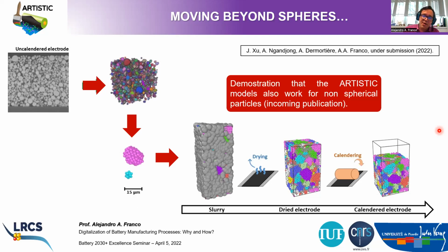And here, what we did is we start from tomography images, micro CT tomography images. Then we have developed an algorithm which is able to extract the real particle morphologies from these micro CT images. And then we perform all the simulations of the slurry, the drying, and the calendering using the real particle morphologies, okay? And then, of course, we compare the outcomes in terms of microstructure with what we get from tomography, once again, for different formulations and for different compression degrees.